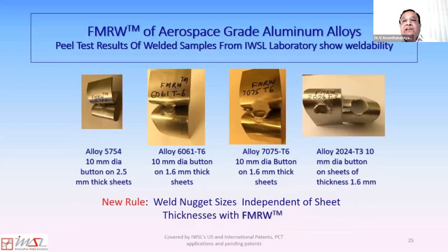And when you cool the heat affected zone, some of the non-weldable aerospace grade alloys become very weldable. As you see here, the alloys 7075 and 2024 T3 have very good buttons, and they had good microstructures as well. Due to a lack of time, I'm not going to show microstructures of these alloys. And what is also important about this focused melt resistance welding is that the diameter of the weld in all these cases is the same, 10 millimeter diameter button.